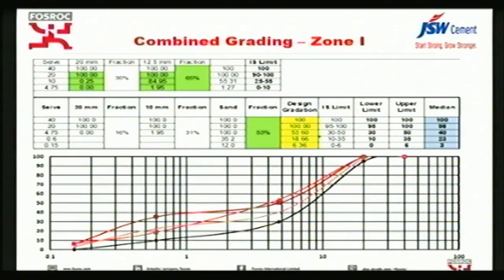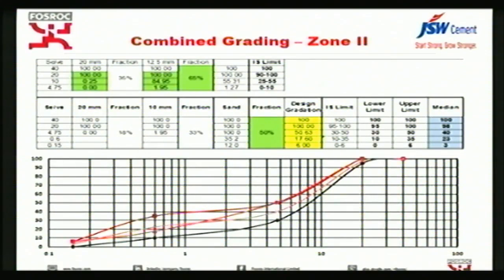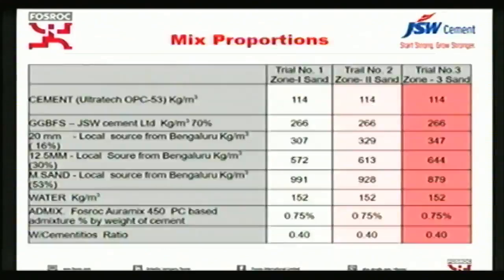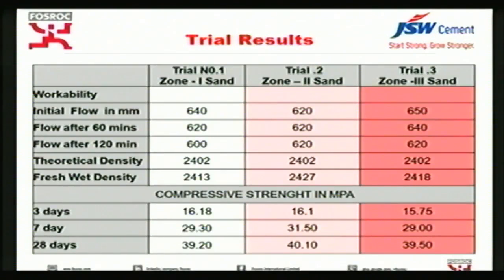This is the zone 1 sand and 53% sand. Similarly, this is zone 2 and zone 3. So we did some trials before coming here. I would like to show both the rheology and the 620 flow. Even after 1 hour, 620 mm flow, and even at 120 minutes there is no reduction in the flow. And these were the theoretical densities and fresh weight density. At 3 days we got around 16.1, we also measured the 7 day strength, and 28 days around 40. And similarly for other zones, what we got in this range.